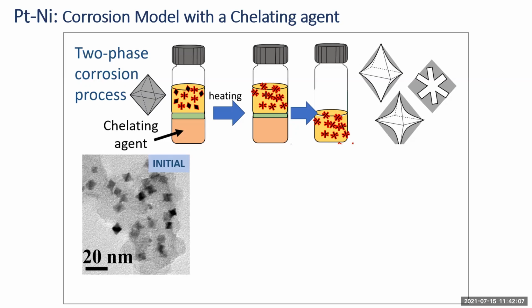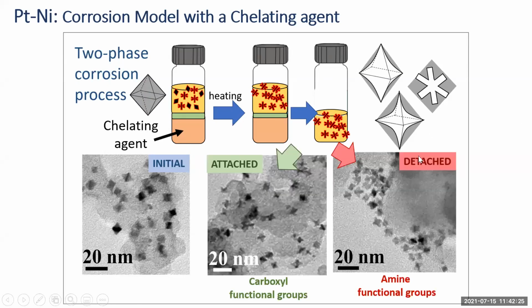So we can see how, in the environment of the carboxylic acid and other environments, this particle will change its morphology. Initially octahedral, because it's the shape that was optimized for this type of catalyst, and how it looks in the end. And I will spoil it a little bit, but the important thing is that, depending on the organic group that you have here, depending on the chemistry, the particles will detach or not detach, and we will see that now.